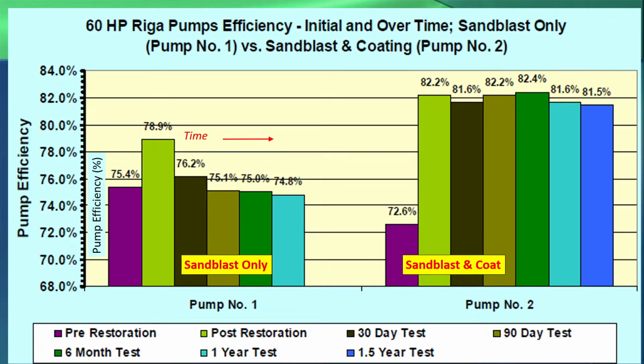Well, here you see after 30 days, after 90 days, after 6 months, and after 1 year. So 1 year is right here where you're at 74.8. You're not doing anything. In other words, you've spent that money to get that sandblasted, maybe even did a little bit of mechanical refurbishment, replaced some seals. It's really not going to hit that well.